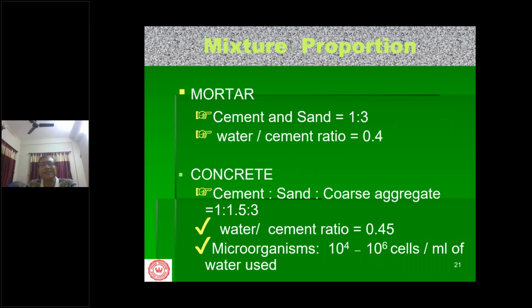Now, these are the mix proportions. We used cement to sand 1:3, and we took a water cement ratio of 0.4. For the concrete, we used 1:1.5:3 by weight.